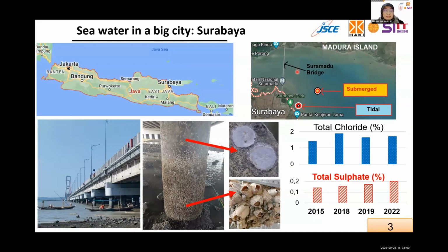We found some signs of chloride attack on the bridge, especially the bridge piers, with many barnacles, as we call them here, attached to the surface of the piers. We have been observing increasing sulfate and also chloride together from the seawater. And we know that this is a great concern, as chloride is not the only threat, but also sulfate penetrating the concrete, resulting in reducing, of course, the service life of the concrete structure.